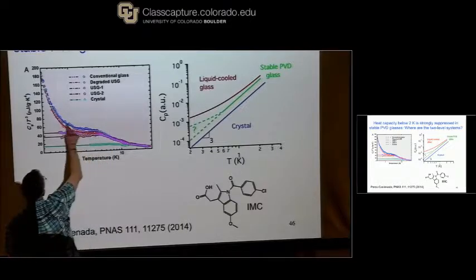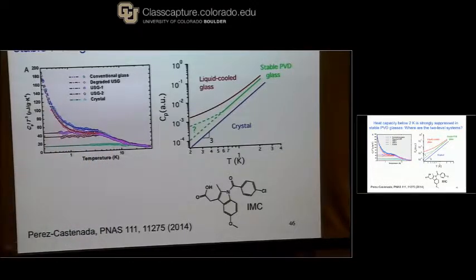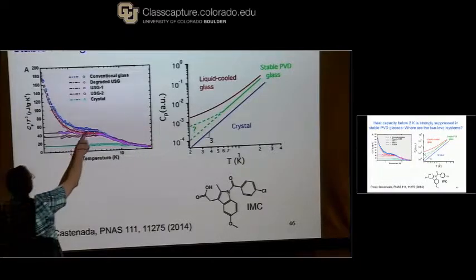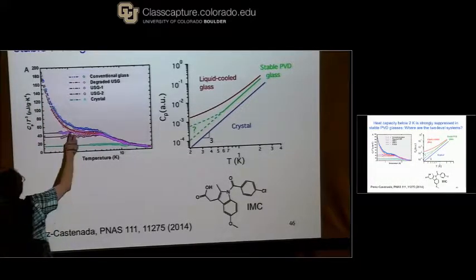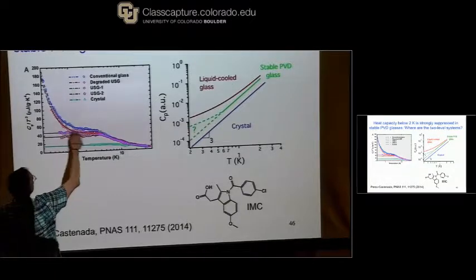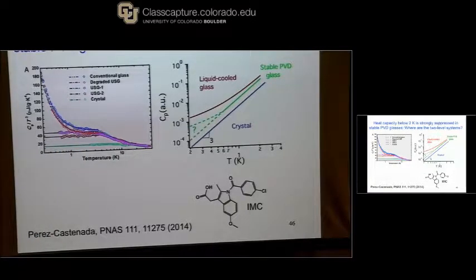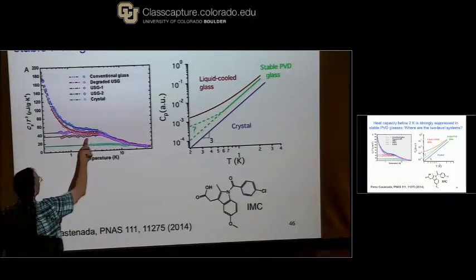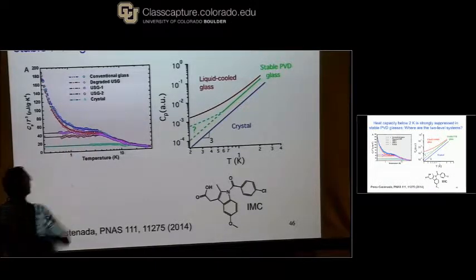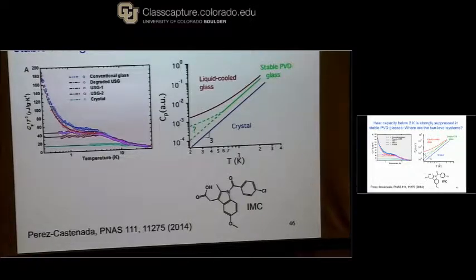Conventional glass, this is the liquid-cooled glass. You see when you plot Cp versus T cubed, it's shooting up. Okay, that's because it's basically going linear. Okay, and so this is what's happening in a liquid-cooled glass. These two are two different samples of vapor-deposited stable glasses at 0.85 Tg, the same temperature I've been telling you about for indomethacin. And in this regime, below 3 Kelvin, they're consistent with a T-cube scaling.